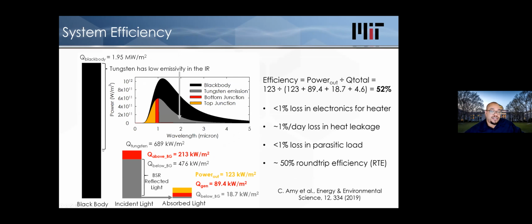But what we actually want to do is we don't want carbon to do the emission. That's another issue I could talk about. But in short, carbon's vapor pressure is too high, and we'd like to actually have tungsten facing our cold PV. And so we want to put a layer of tungsten in front of it that prevents the carbon from getting to the PV cells. And you take a significant hit, though, on the power density because tungsten is a reflective metal, so it actually does not emit as much light. So here's now after the penalty you pay with tungsten. You get less than a megawatt, closer to 700 kilowatts per square meter coming out of tungsten.